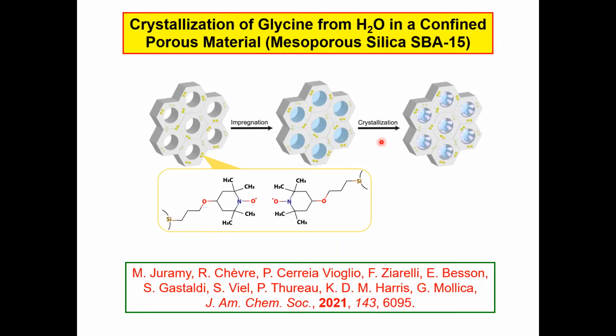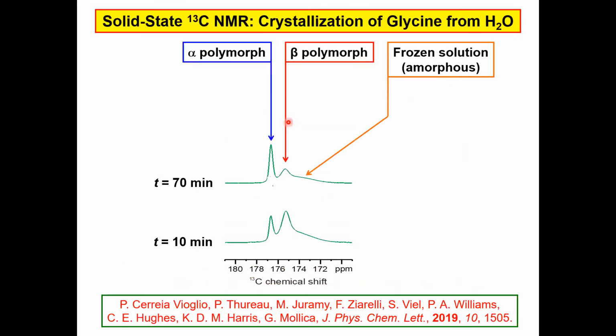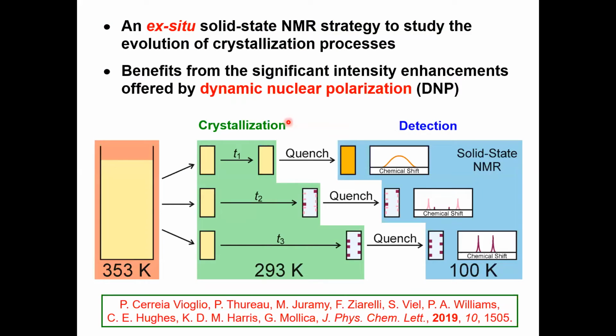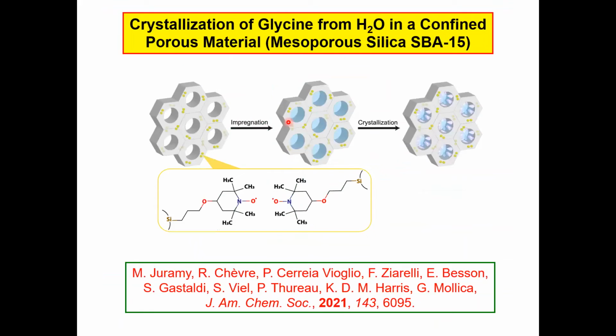And just very finally, a more recent paper as part of this collaboration was looking at crystallization of glycine in confined porous materials. The big advantage here is that the polarizing agent can be embedded within the porous material and therefore will not interfere with the crystallization process. One of the questions, although we do various control experiments, is, does the polarizing agent influence the pathway or the mechanism or the kinetics of the crystallization process or not? That's avoided in the crystallization here. So that was really just touching upon another opportunity to study crystallization processes by NMR.